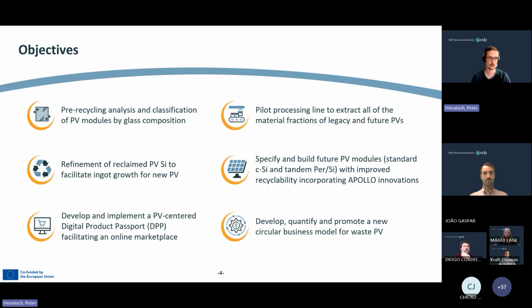So in total, we constructed 6 objectives for our project. First of all, we want a pre-recycling analysis of the PV modules before we send them for the processing, just to distinguish the modules in their antimony content. Because if we use glass with lower antimony, we can go into different glass markets than with glass with a high antimony content, where we only can go more or less back into the PV market of pressed glass sheets.